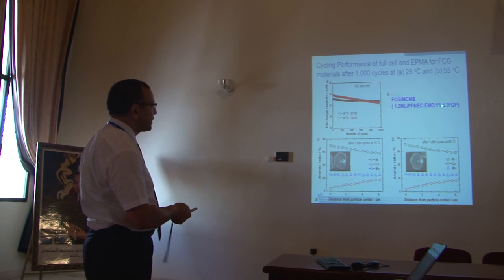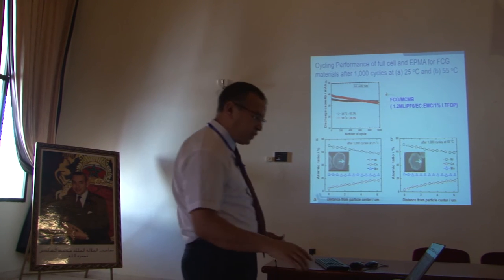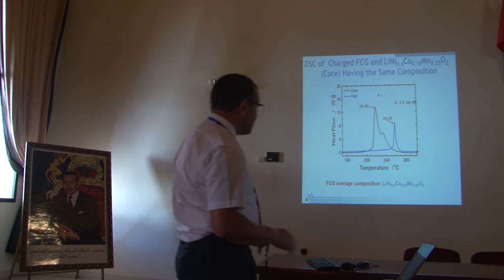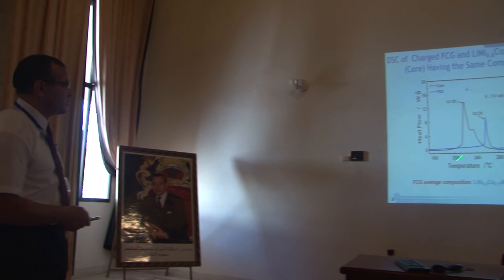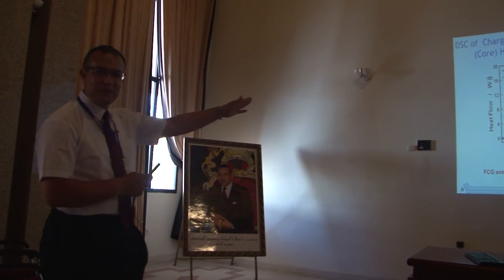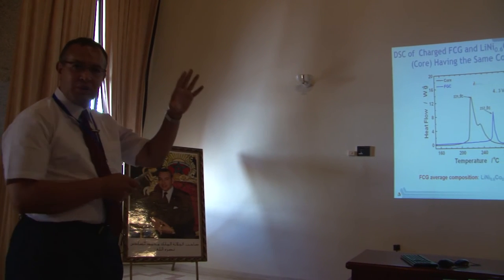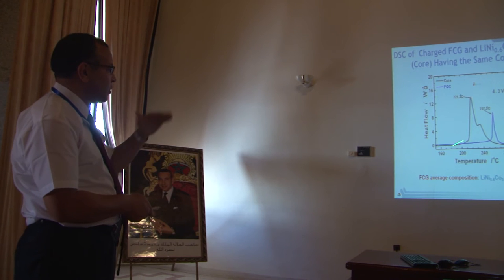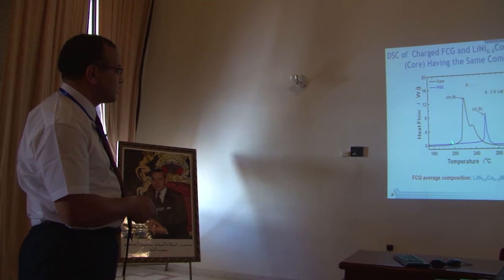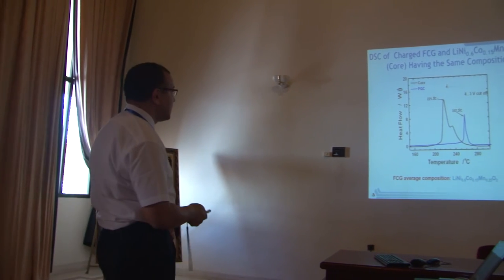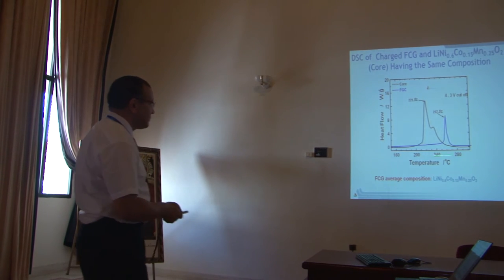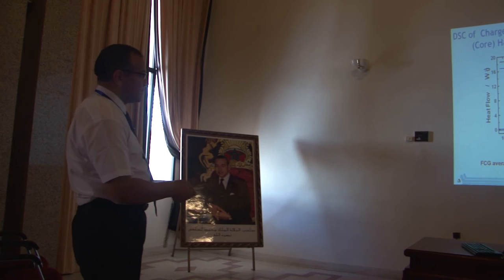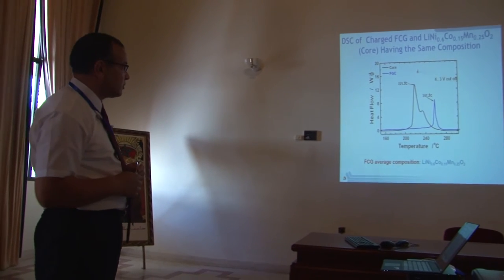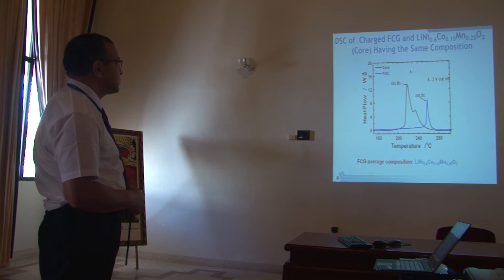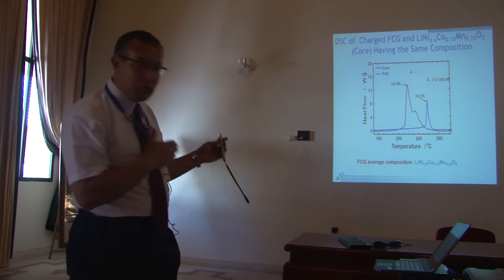Of course, in this case, we have to protect the carbon, so we use an additive that polymerizes when you do the initial formation and forms a passivation film that is very stable. On safety, since we increase the concentration of manganese at the surface, this is a differential scanning calorimetry. I was telling that lady, this is what you need to do for safety. You charge your electrode, add electrolyte, and heat it up slowly. And you see clearly the onset temperature of the NCA is very low, which means the activation energy is low and reactivity is fast. And the overall heat, which is proportional, fortunately I didn't put it here, to the surface area of this peak, is very high, compared to the gradient, which has a much higher onset temperature, because, again, it takes more heat to create reactivity, and the overall reactivity is very low. So not only do we improve the cyclability significantly, but we also improve the safety.